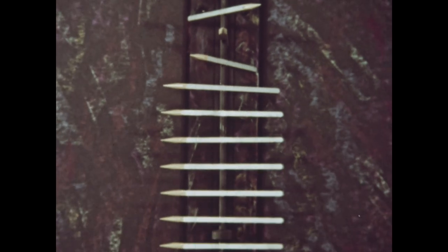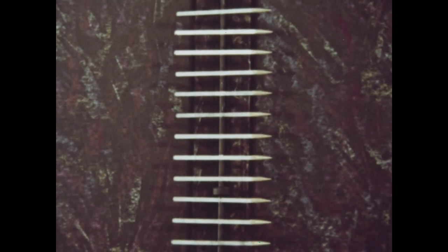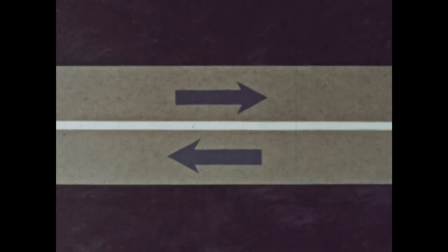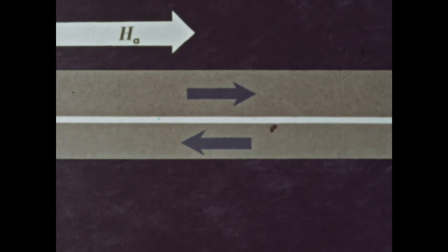Thus, the wall can move without encountering either magnetostatic or magnetocrystalline anisotropy energy barriers. Consequently, if we apply even a weak field, the wall moves. One domain grows and the other shrinks because this lowers the energy of the system right from the start.